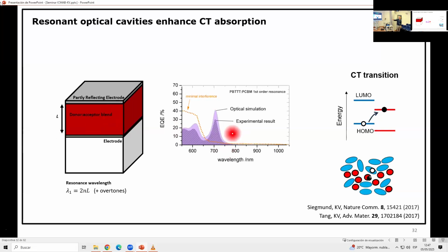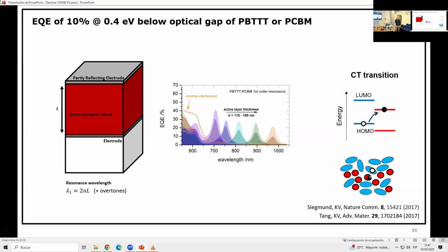We just basically replaced one of the electrodes with this partly reflecting electrode. And you already see, also with modeling, and the modeling is the slightly higher one always, the experimental result looks a lot like it, just a bit lower. You can increase the absorption, in this case maybe 10 times. But the nice thing is also if you change the thickness here, the wavelength of that standing wave is longer, and you can keep going. And something where it looked like there was no response before, now all of a sudden has a response.